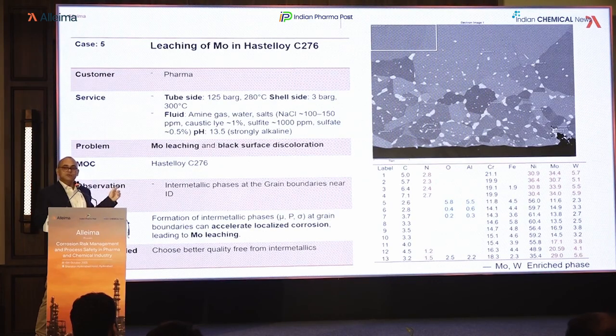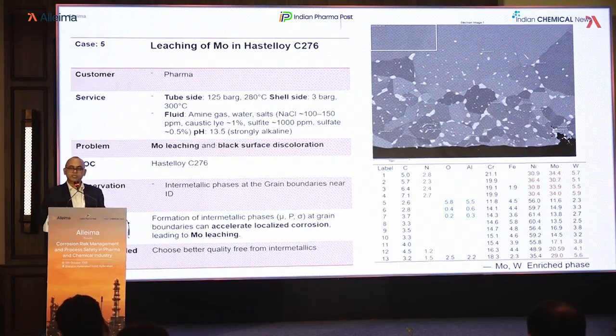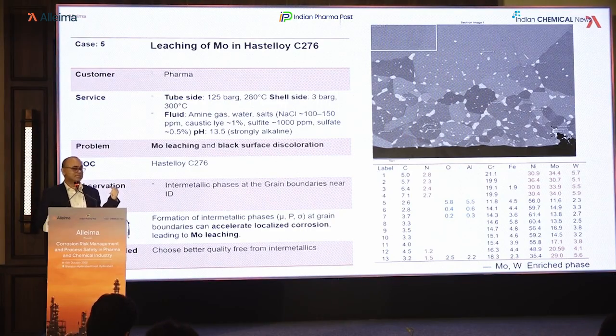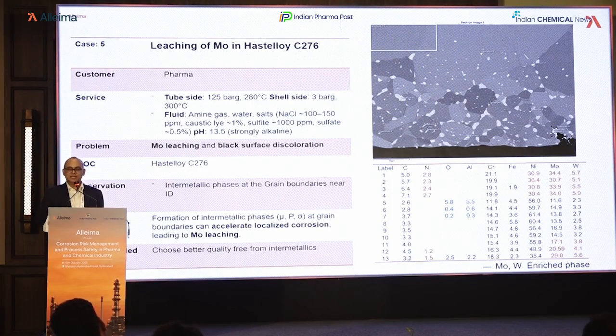All right, so this was again very, very interesting and very relevant. So there was a customer in the pharma, and what they complained is that they had moly leaching in alloy C276. This is the Hastelloy, and this is known for very high PREN number. So Hastelloy is a very good material actually, and you should not have such a problem. And this was really, like your entire batch was getting bad.